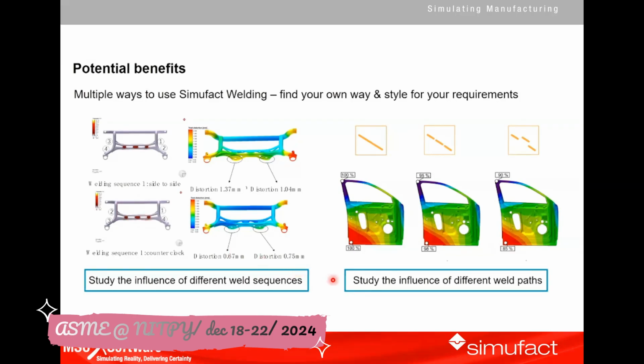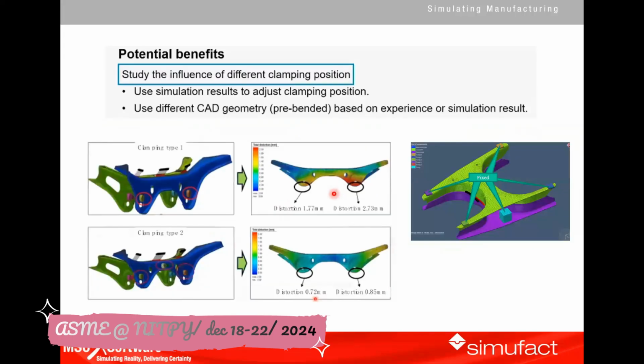Okay. And we can also study the sequence for different weld paths. For example, this is a car door assembly which is welded. And here you can see if you use a continuous weld, a discontinuous weld or a staggered weld like this, how the distortions at the end can vary. Even though the pattern is the same, the magnitude of the distortions might be different. Okay. So these kinds of studies can be done very successfully using the Simufact Welding software. And another case study here is studying the influence of different clamping positions. This is a finite element model of components, and here we can see the clamps which are there on the components. These clamping geometries have an influence on the welding results.